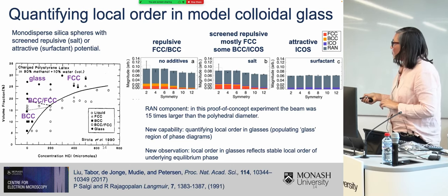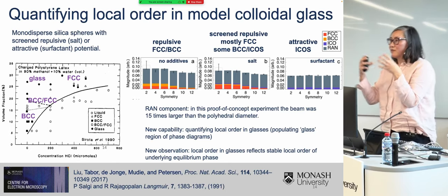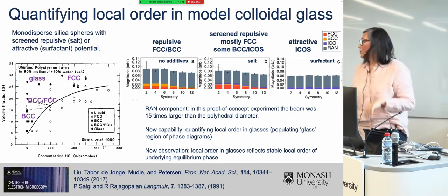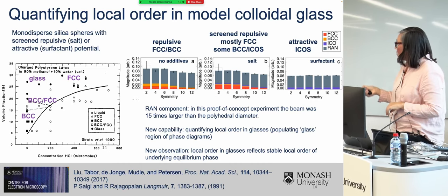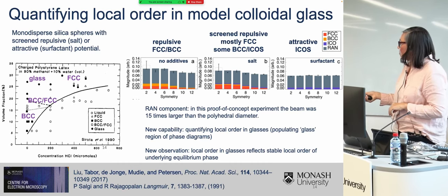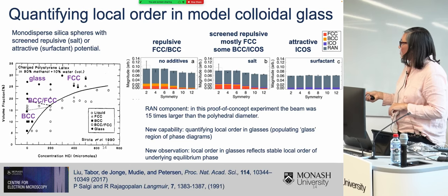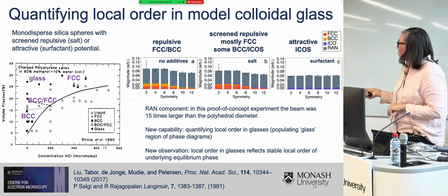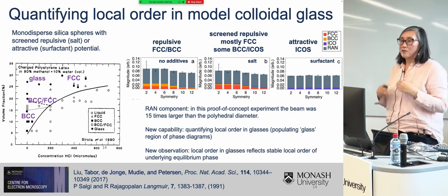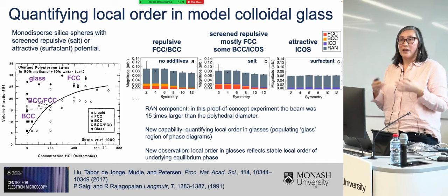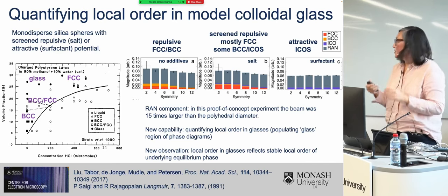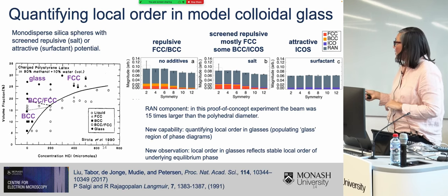And so the equilibrium phase is BCC, which is the spheres trying to get as far away from each other as possible. But then as you add a little bit of salt, you can screen that repulsive interaction and the equilibrium phase becomes FCC. And then you can also change the interaction by adding some surfactant, and this will make the interaction completely positive or attractive. And then at very high volume fraction, you obtain this glassy phase here.